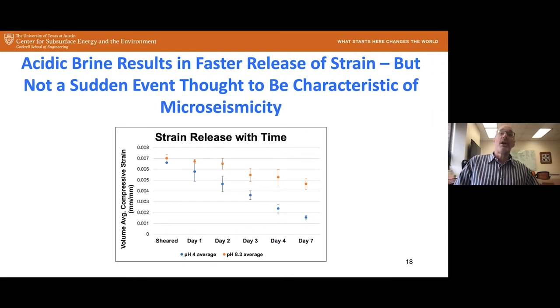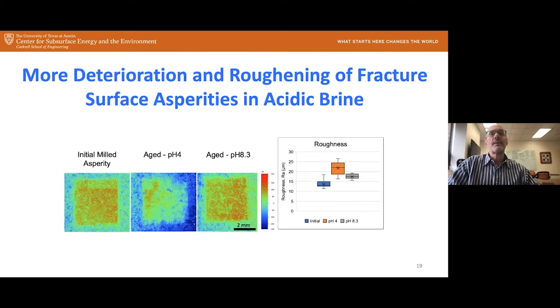So here was the main result, and one that we had postulated would happen. And that was that if you look at this volume average compressive strain, it decreases more quickly over time for the case with the lower pH than the higher pH, all right? And so basically it's showing that because of the lower pH, it is weakening the reservoir rock or this Bandera gray sandstone. And then these contact points at the asperity are yielding and allowing that strain to be released over time. And so the next task was in interpreting, or I think more kind of supporting our expectations of why this is occurring or did occur. So the first thing we did was laser profilometry, looking at these asperities.